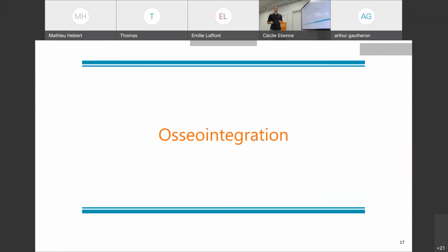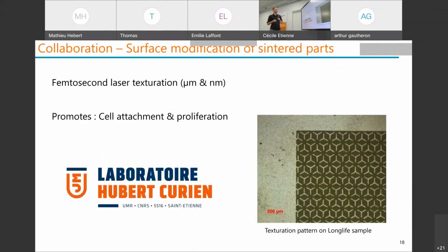So this was about rheology, and the last part I want to discuss is about osseointegration. So we will try to make this part at the end when I will have good ceramic parts, and we will work in collaboration with a laboratory with femtosecond laser texturation in order to promote cell attachment and proliferation at the surface. So we'll have to find an optimization because we want good mechanical strength, but we also want to have a less dense part and to make specific patterns to promote the adhesion and also the bone growth on the surface. So you can see on the right a result that has been made with samples that have not been printed, but of the same type of ceramics that is used.